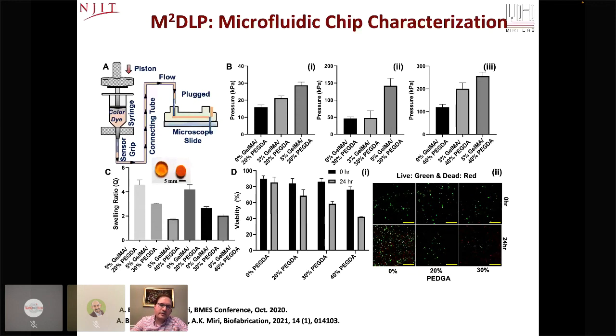Another aspect, when you're looking from the perspective of making a disease model, you are interested in the swelling ratio, how the swelling behaves in a fluidic environment. You can see the material was fairly stable for swelling ratio. And then biological response. When you have PEG, you always have viability at just the beginning. But over time, you want to work with a gelatin-based system, where the gelatin helps you keep the cell viability after 1 day, 2 days, 3 days, which we tried to show.